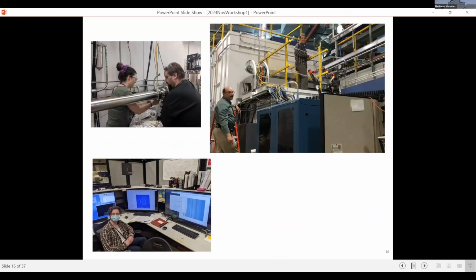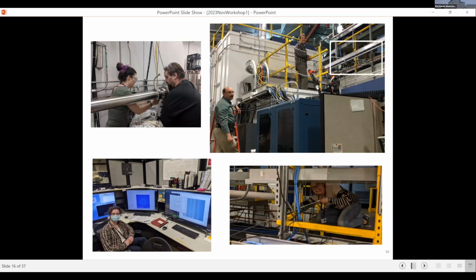So one of the things we did was I had 2 different graduate students spend time at a beamline to build a furnace so that we could do in situ X-ray diffraction measurements, in other words, as a function of temperature, because we can't tell what the best temperature profile is. But if we do in situ X-ray diffraction, we could figure out what's growing at what temperature. And then we could use a small amount of sample and grow larger single crystals. So that was a lot of fun. And actually, the furnace is still at 11-BM. So someday when APS is up and going, that will be available to the community, which we're really excited about, for the growth community.